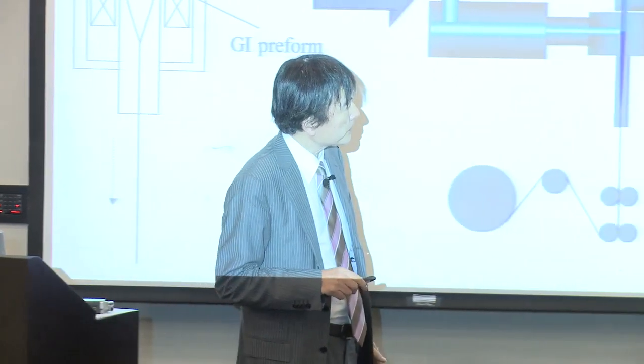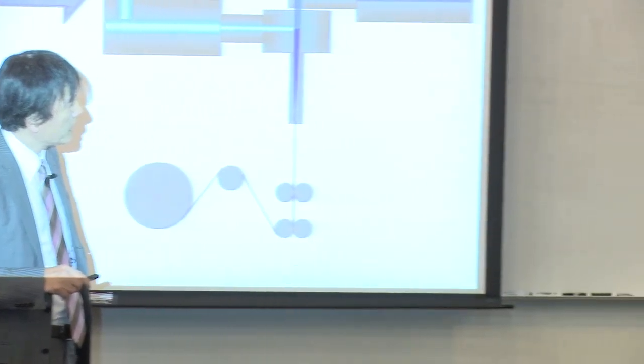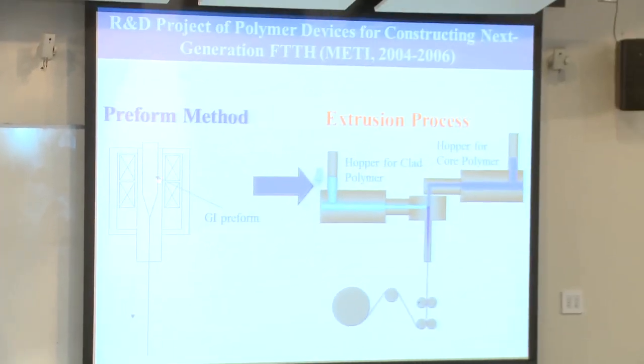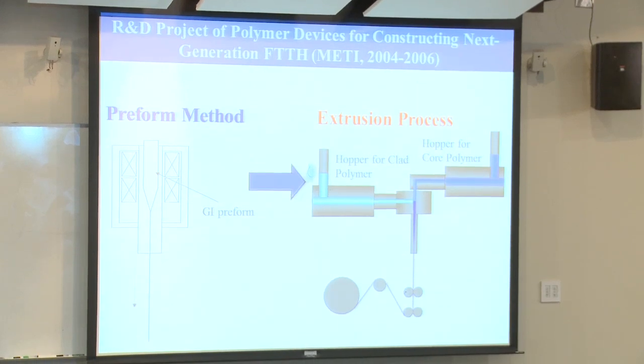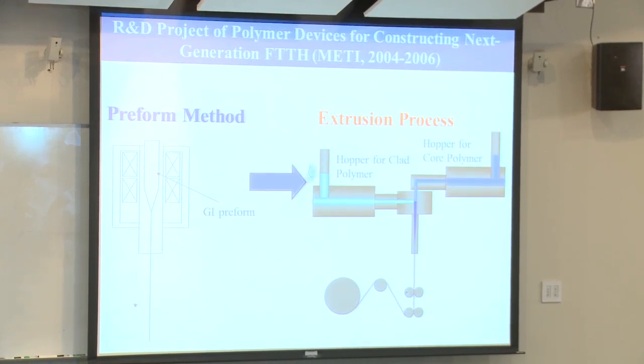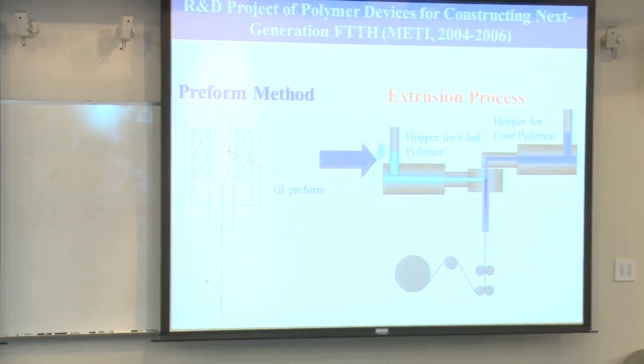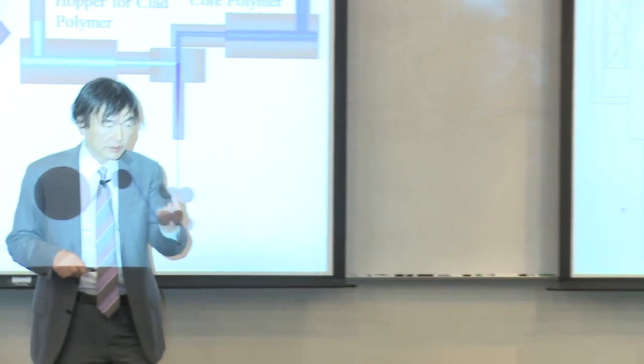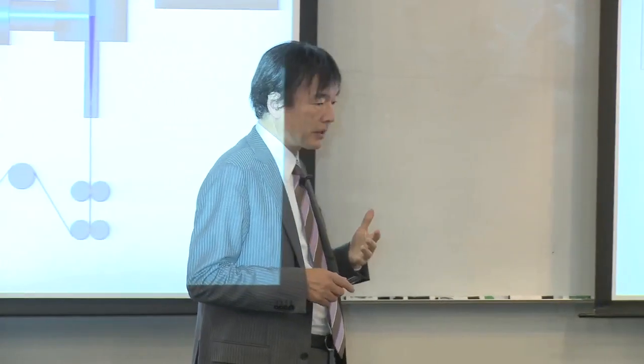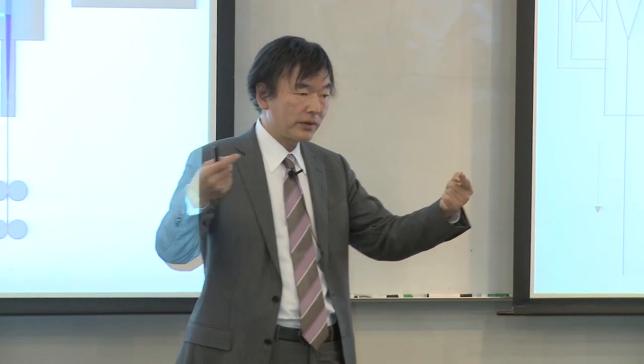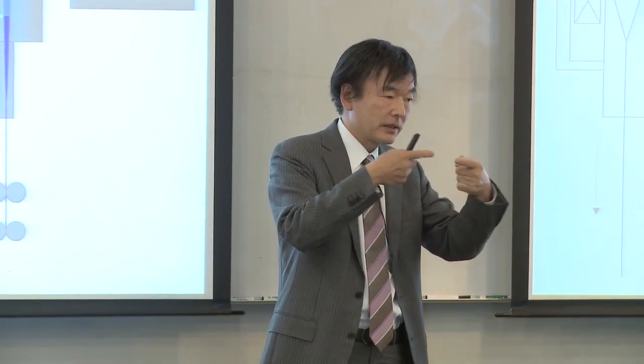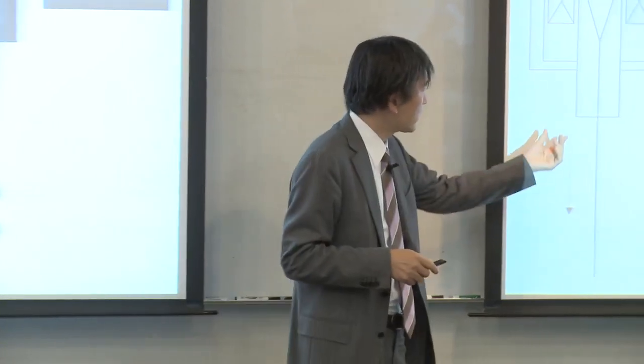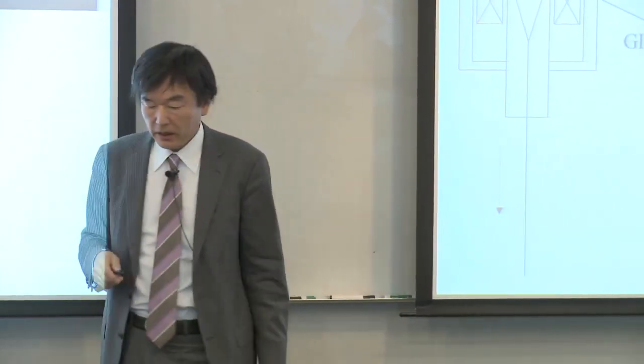Then, first the graded index profile was obtained in the preform state. And this preform rod is heat drawn into the fiber. But considering the process cost, especially compared to the silica optical fiber, silica optical fiber is very thin. But the advantage of the plastic fiber is the large core, so easy connection can be made. So considering the drawing ratio, plastic fiber has this advantage.